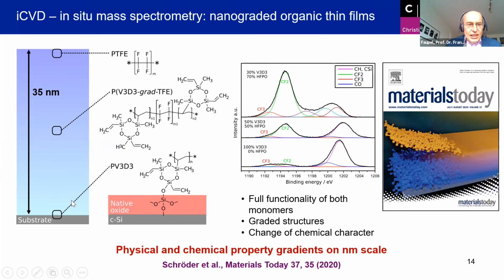Here's one example where we used a monomer which attaches to the native oxide of silicon, and this makes available the technique for the semiconductor industry. If you can make such films with a very good covalent bonding to silicon wafers, this is a real important requirement for microelectronics application. And then we can tailor within a few nanometer to make any functionality on top.